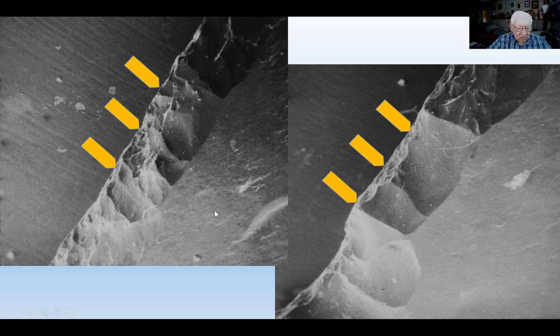because in this direction it was relatively easy to obtain blades and other implements they produced. And there are examples of the edge of implements from Tel el Farkha with traces of retouche, and this retouche is done parallel to the orientation of small crystals of quartz present inside.